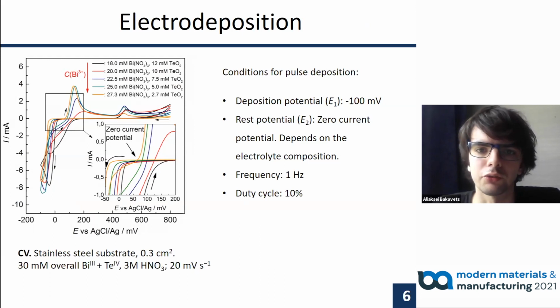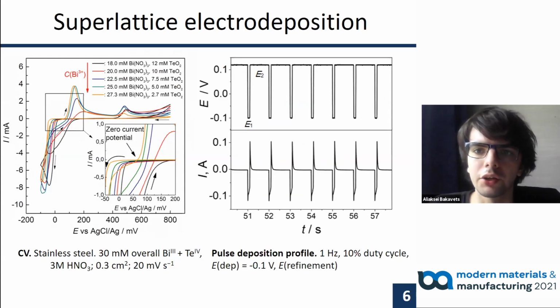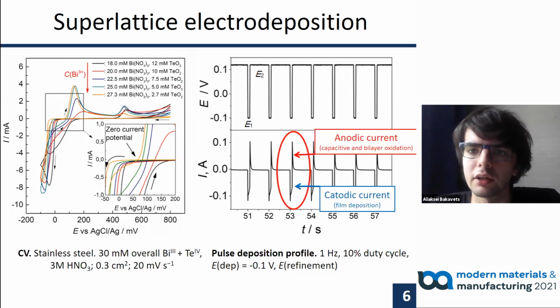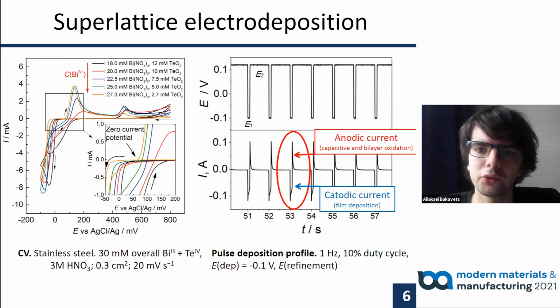For the electrodeposition of the films of Bi2Te3 and superlattice structures, we chose the pulsed electrodeposition mode with a square potential waveform. Deposition potentials were determined from cyclic voltammograms. Here are the potential and current profiles in the pulsed electrodeposition of the superlattice. The cathodic current is attributed to the film deposition. Anodic current prevents nucleation of bulk bismuth and controls bismuth interlayers.